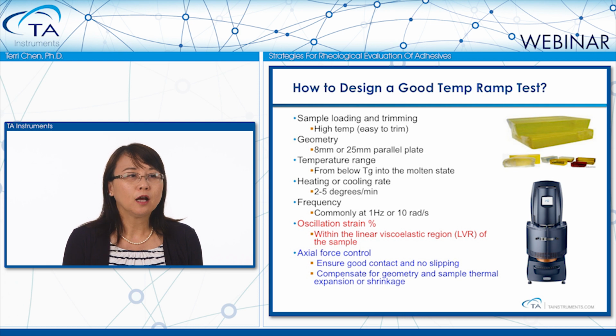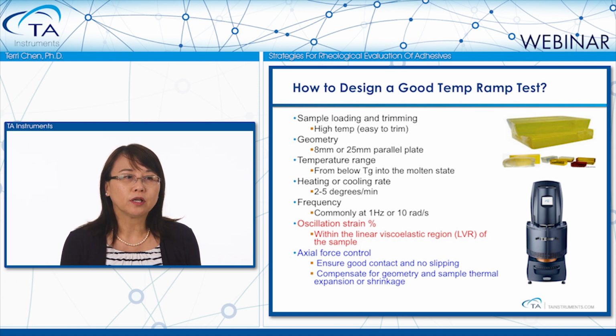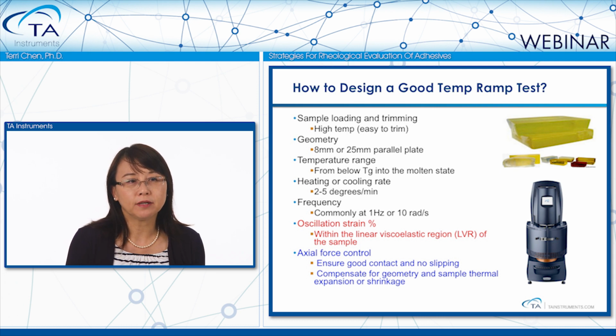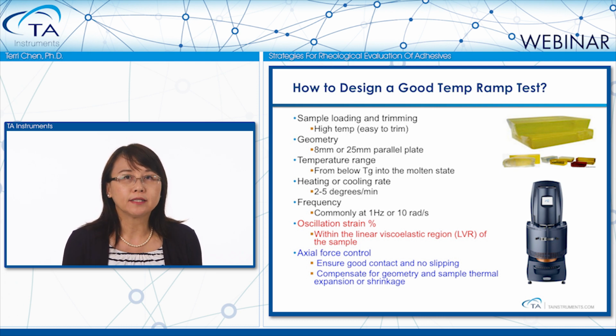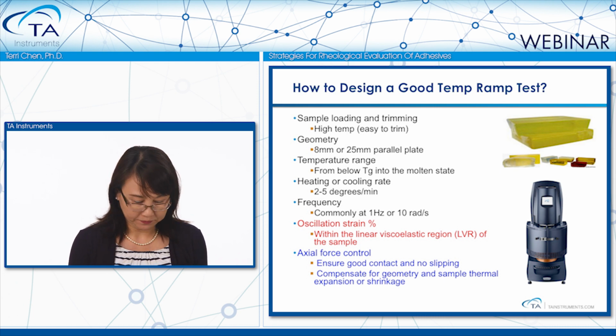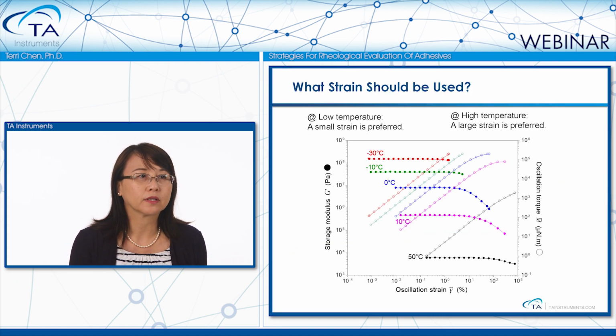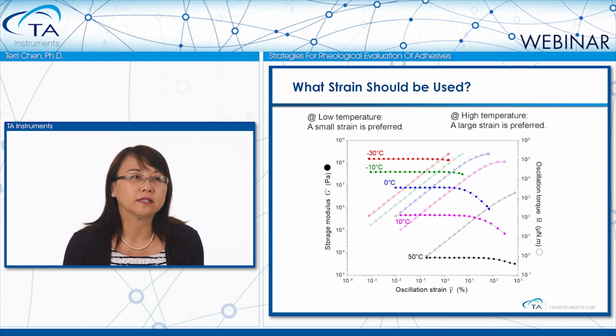In addition, both sample and geometry will expand or shrink as we change temperature. So it is important to have active axial force control to avoid sample slipping and also compensate for sample and geometry expansion and shrinkage. As we have just mentioned, setting up a good strain is the key to getting good temperature ramp experimental results.